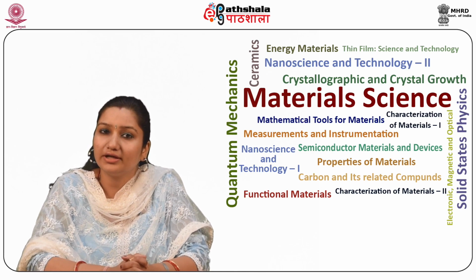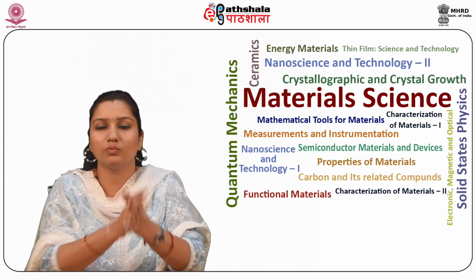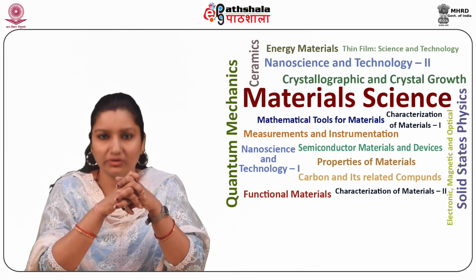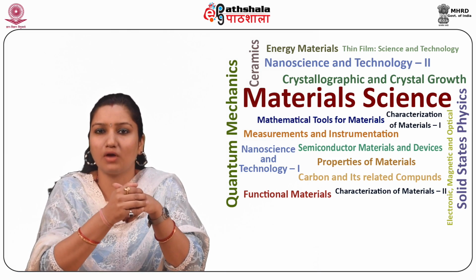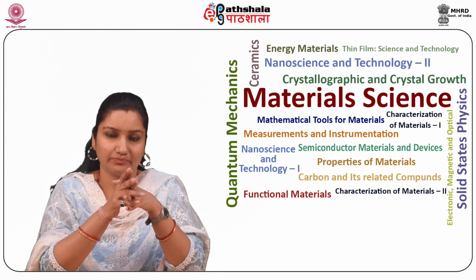Typically, a 13.56 MHz power supply with 1 kilowatt to 3 kilowatt power and about 2 kilovolt peak-to-peak voltage is used to couple the cathode through a matching network.